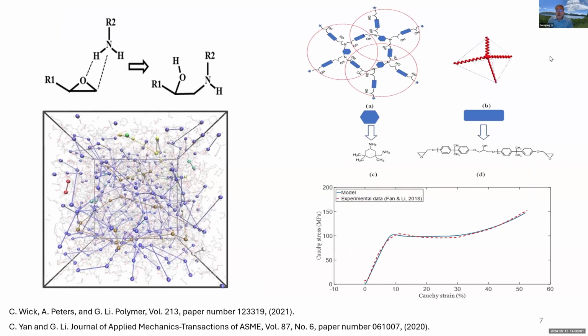So we are also trying to see if this idea is universal or not. Basically, what we did is use dynamic molecular simulation, and we also use solid mechanics modeling, and we compare the modeling result with the experimental result. We found that yes, this idea is correct. The bond length change and bond angle change indeed can store the input energy.